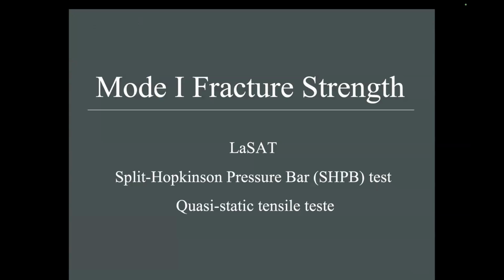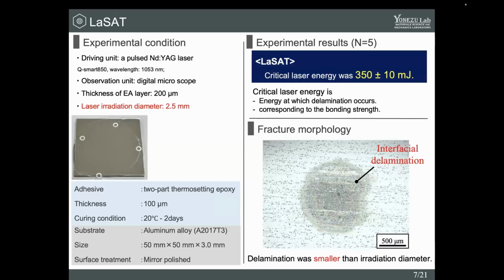Next, I'd like to talk about mode 1 fracture strength. First of all, we conducted LASAT. As a specimen, on the top surface of a mirror polished aluminum alloy, epoxy resin adhesive was cured with 100 micrometer thickness at room temperature for 2 days.